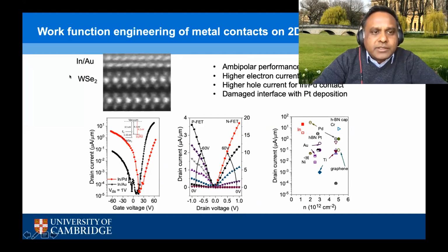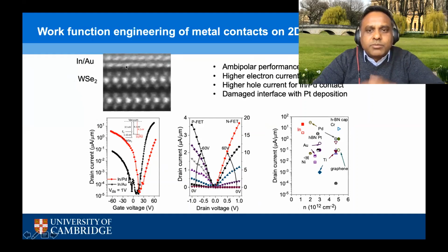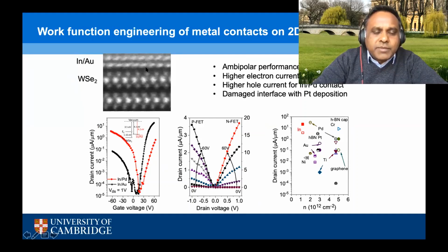So here we made devices on tungsten diselenide, and here we show indium gold as the electrode, but we get similar interface characteristics with indium palladium as well. If we look at the transfer characteristics, with tungsten diselenide and indium gold as the electrodes, we get this black transfer characteristic where one can see that the electron current part dominates with much higher current. But if we make electrodes with indium palladium, we can increase the hole current quite dramatically with respect to indium gold.